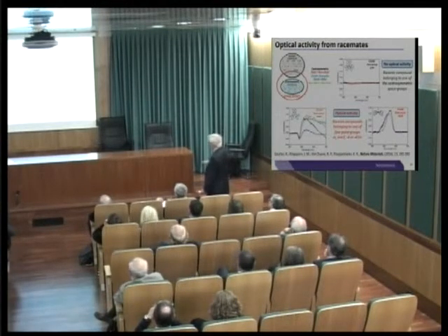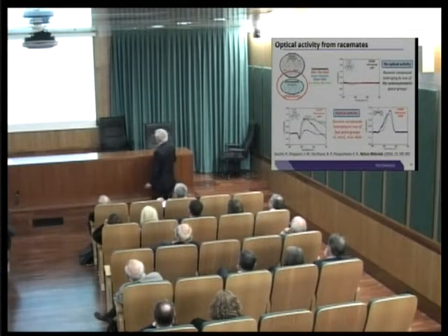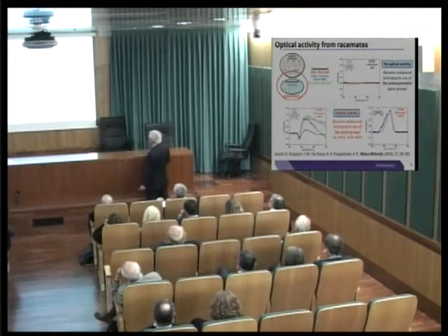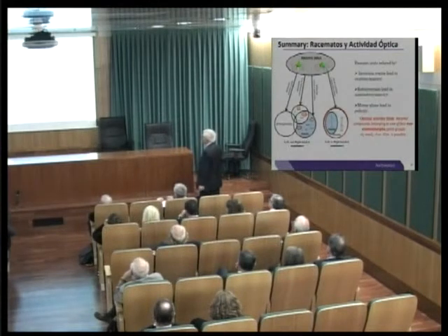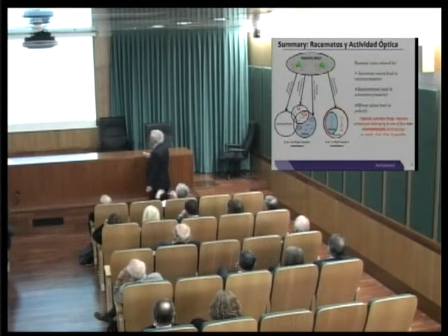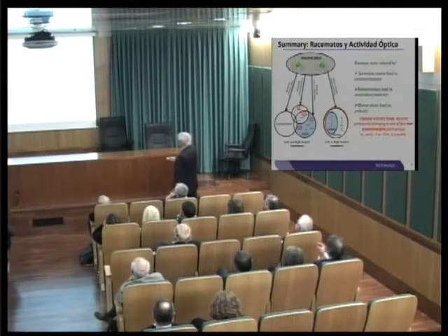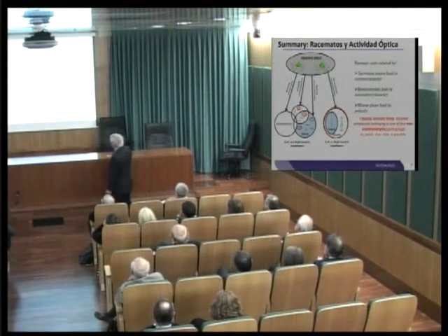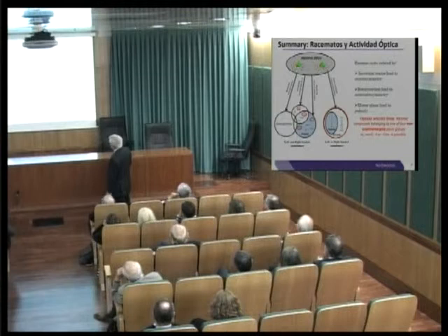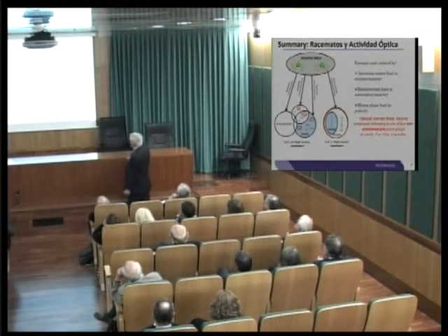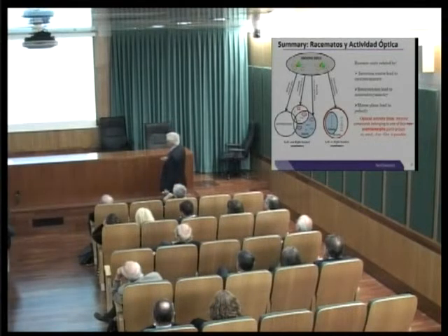We also did this with another enantiomorphic compound, again with a bipyridyl ligand, two of them, but with this different symmetry, but this also is non-centrosymmetric and chiral. So here's a summary then of racemates and optical activity, showing some of the molecules or cations that we use. So if the two enantiomers are related by an inversion center, this is centrosymmetric. If they're related by rotoinversion, one would have these cases, and these two are the two polar ones. If they're related by mirror or glide planes, then you have polarity, all of these, and these are the two